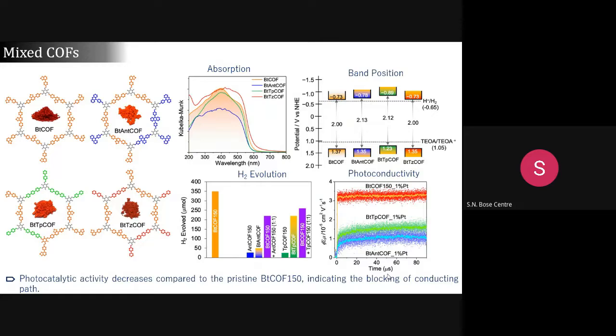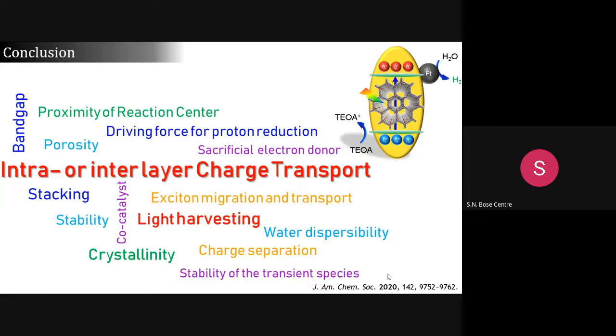Cracking, crystallinity, and all others are very important factors. But one of the major factors is the intra- or interlayer charge transfer. If you increase the porosity from 1000 square meters per gram to 2000, you may not get the hydrogen evolution twice.